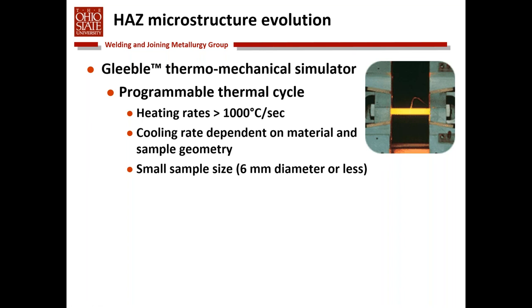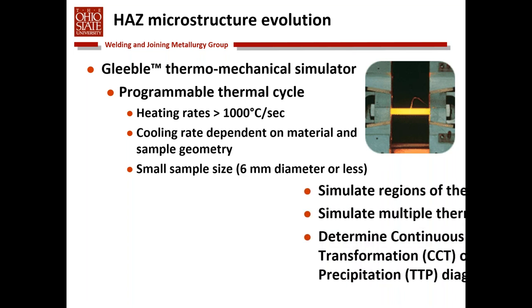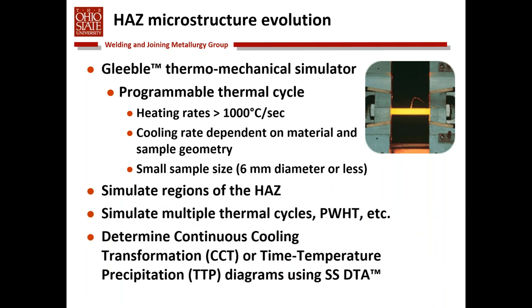So again, the Gleeble is a thermomechanical simulator. It's programmable. I think you know most of these things. The heating rates are relatively high. The cooling rate is dependent on the material, your jaw type, and your jaw spacing. You can manipulate your sample size to generally get the thermal cycles that you need to simulate a given heat affected zone in a given material.